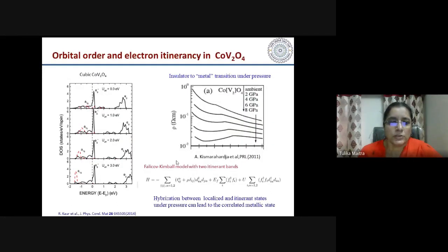Okay, so this CoV2O4 is unique in the sense that it doesn't undergo any structural transition. It remains in the cubic phase, and some time back we had done some calculation considering the cubic phase in this CoV2O4, and because of this cubic phase, this compound is considered to have more electronic itinerancy compared to the other vanadates. And also in experiment it has been seen that with application of pressure it goes to a metallic state.